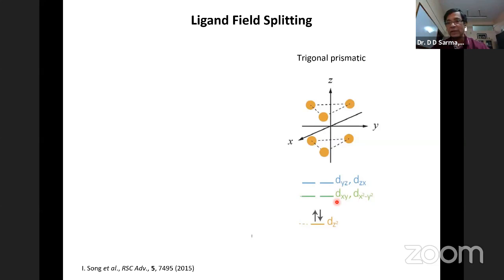Now, molybdenum disulfide with molybdenum in 4+ oxidation state has two electrons left in it. Those two electrons go in here. You can see it's a fully filled shell, and so it's an insulator. And there's a large gap because of a large crystal field splitting and ligand field splitting. And therefore that large gap translates, when I make the solid, an infinite solid made of these units, each of these become a band, of course, but this large gap survives, giving me a large gap semiconductor.